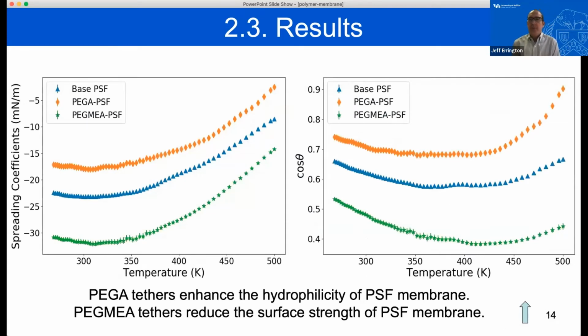As I alluded to before, we then went through a process in which we captured the free energies of the various different states, so the minimum state and the plateau region, as a function of temperature. And that allowed us to determine spreading coefficients and drying coefficients as a function of temperature, and therefore contact angles as a function of temperature. And so here are the contact angles as a function of temperature for the base polysulfone surface, as well as the two non-zwitterionic polymer tethered systems. We see a pretty typical curve here in terms of the variation in the contact angle with temperature. We've seen this in some other systems as well.